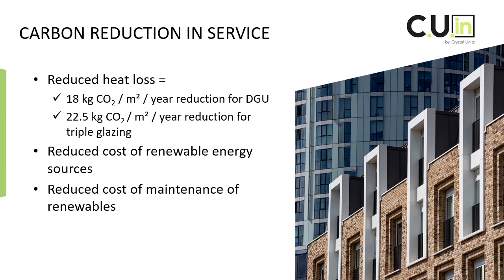Triple glazing with suspended film technology results in 0.2 watts per meter squared Kelvin, which is 0.8 watts per meter squared Kelvin better than standard double glazing. That's 22.5 kilograms CO2 reduced per meter squared of glazing per year through lowering energy demand on the heating system. Consequently, IGUs with suspended film technology result in a reduced cost of renewable energy sources and a reduced cost of maintenance of renewables.